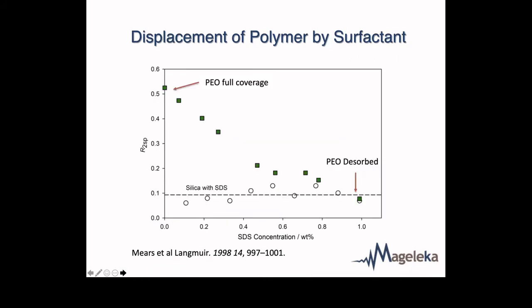This is another nice experiment. Many formulations are complicated. You might have particles, polymers, surfactants, proteins, goodness knows what in a complicated mixture. Can you work out what happens at the interface? Well, one thing that is well known is that polyethylene oxide strongly interacts with sodium dodecyl sulfate to make a polymer surfactant pair. So if you adsorb polyethylene oxide onto silica and then you add SDS, you can see from our graph that the addition of the SDS causes the polymer to completely desorb.